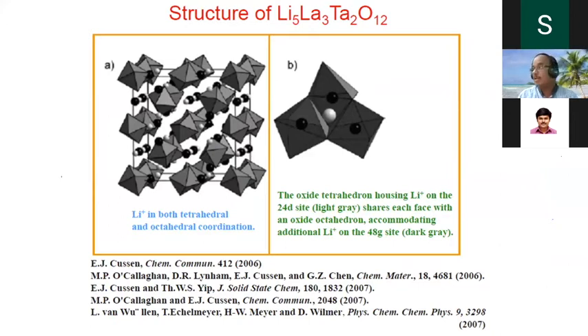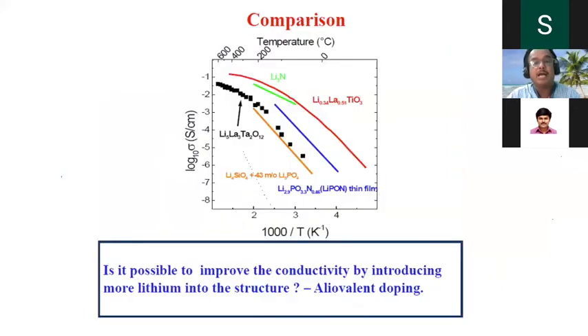Earlier we thought that lithium was housed exclusively in octahedral coordination. We found that lithium is housed in both octahedral and tetrahedral coordination. And very interestingly, there is a partial vacancy in the tetrahedral and octahedral sites, which really helped me a lot to understand these systems. When I realized there is a partial vacancy, with tetrahedral and octahedral coordinations, I could play a lot with these systems. I could improve the conductivity.